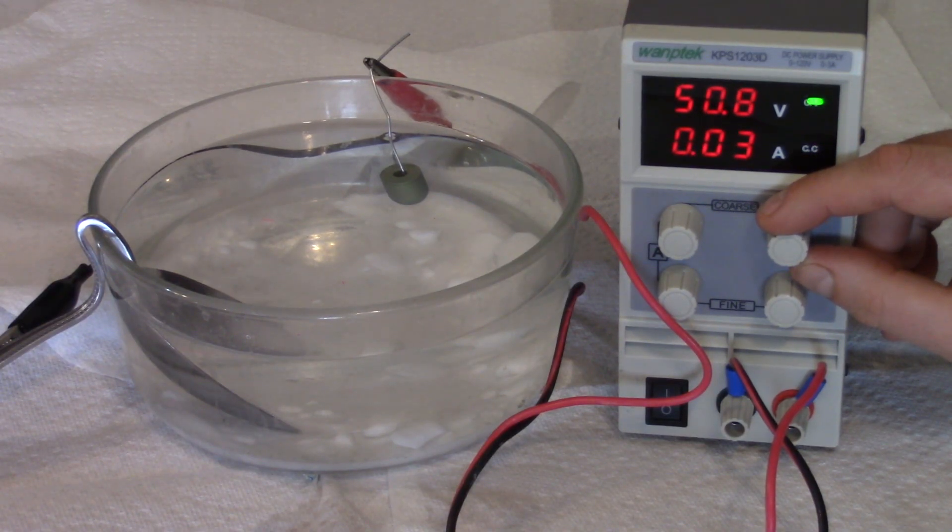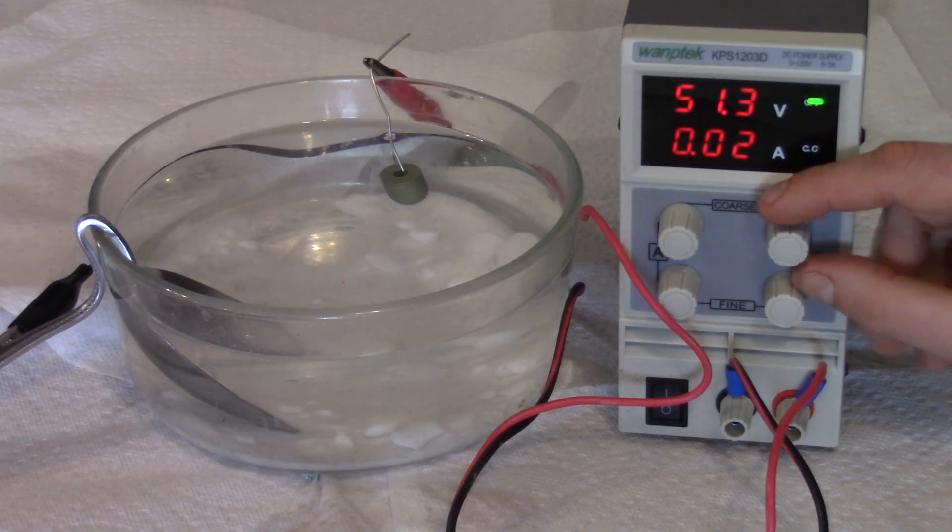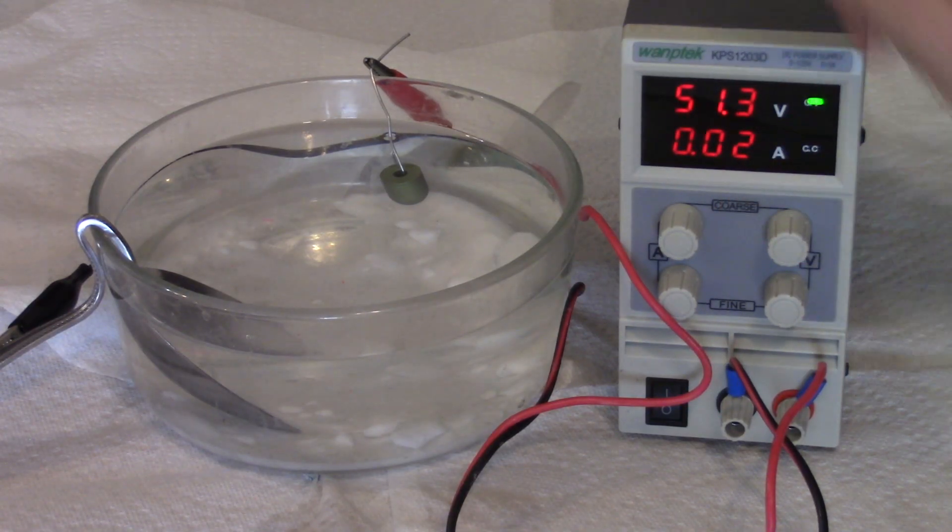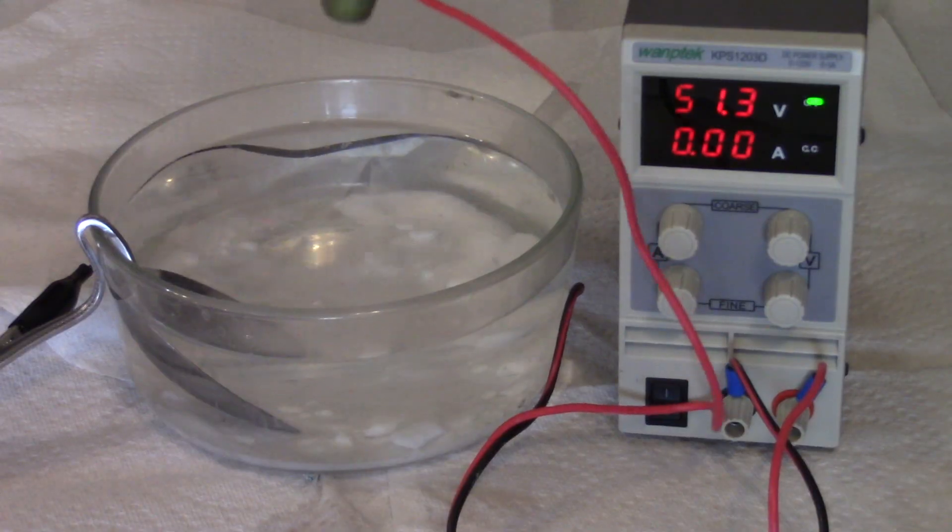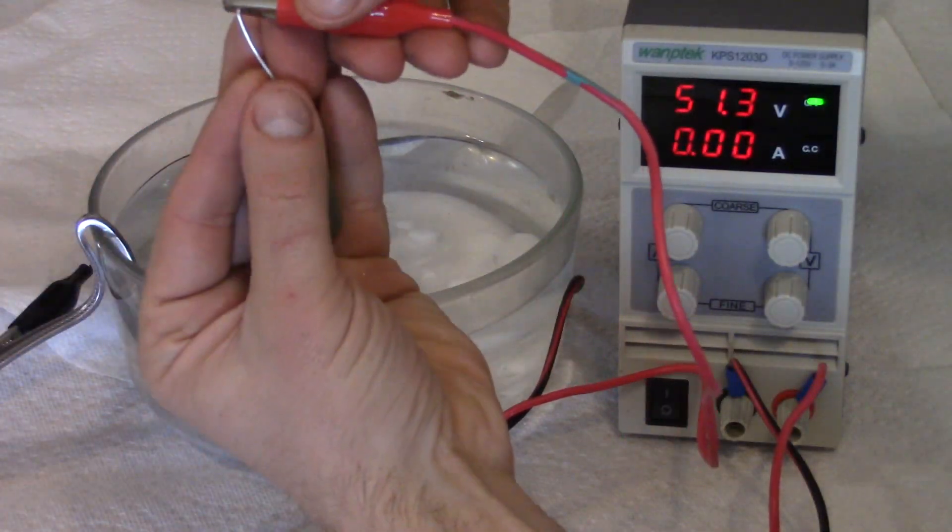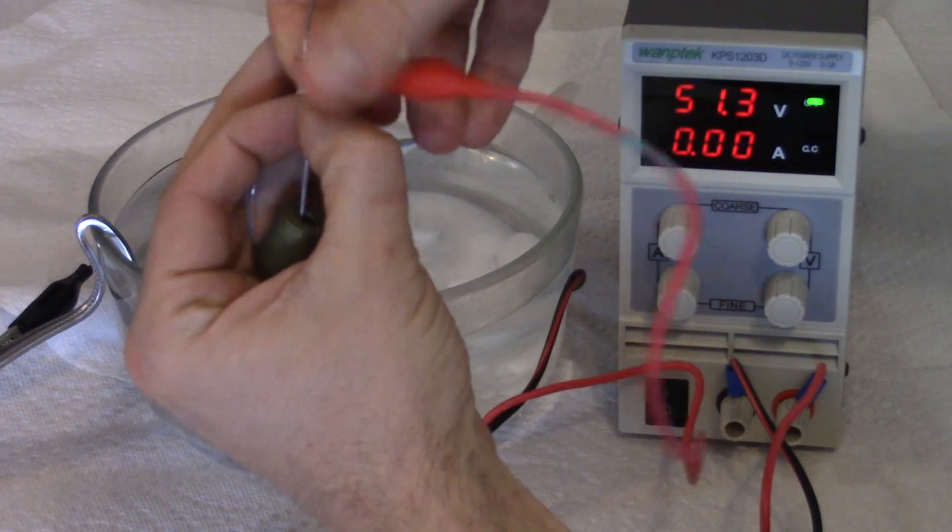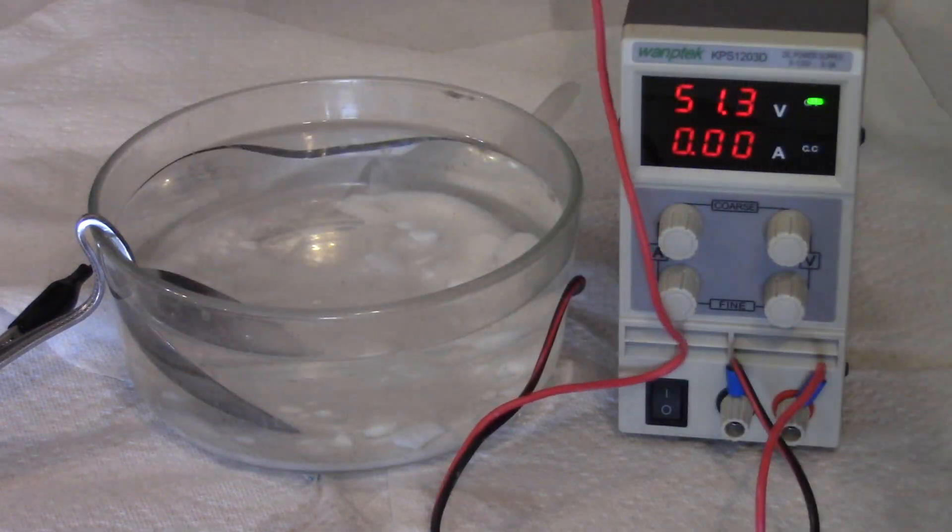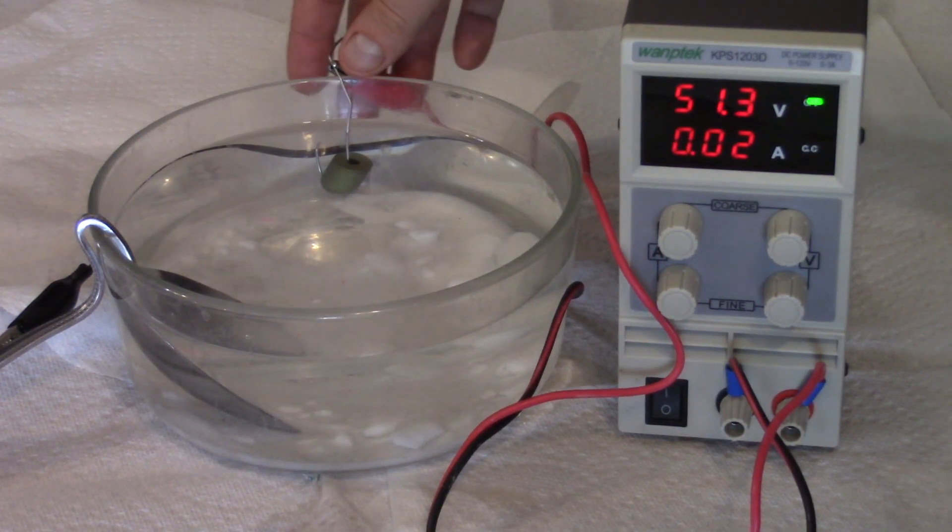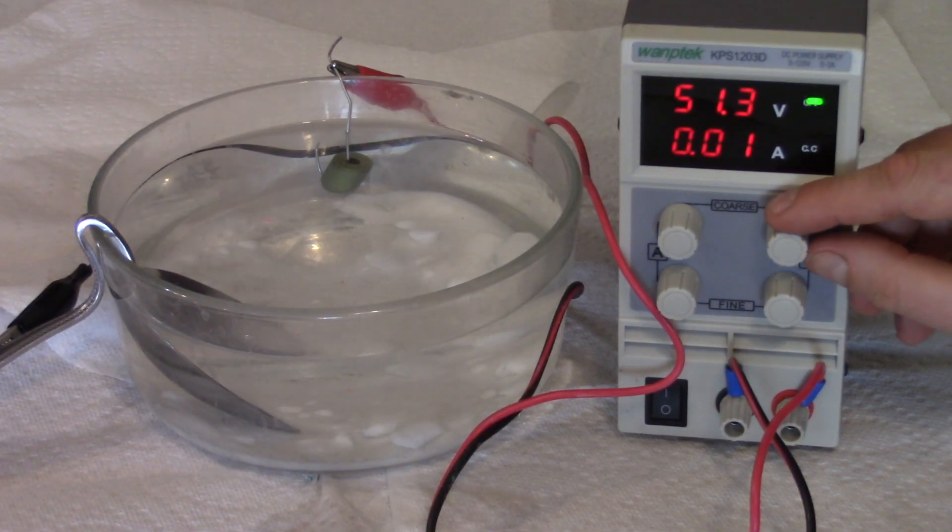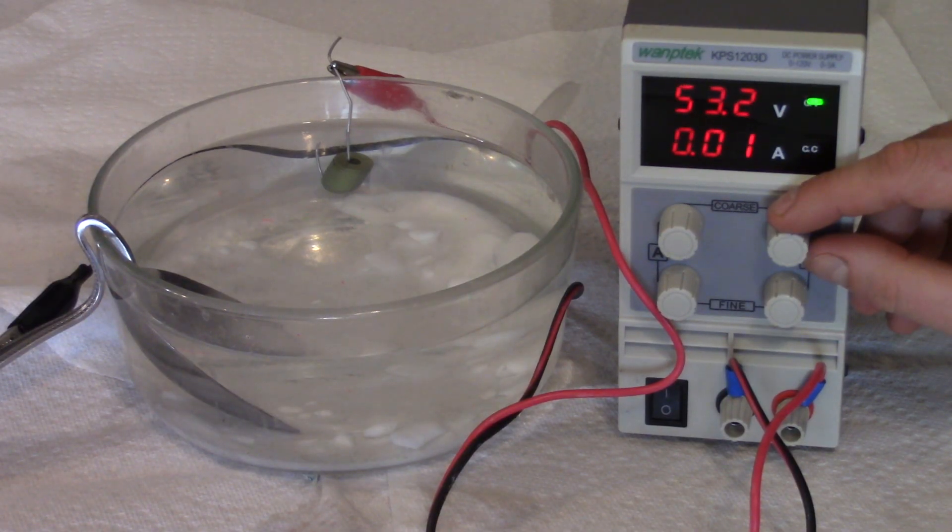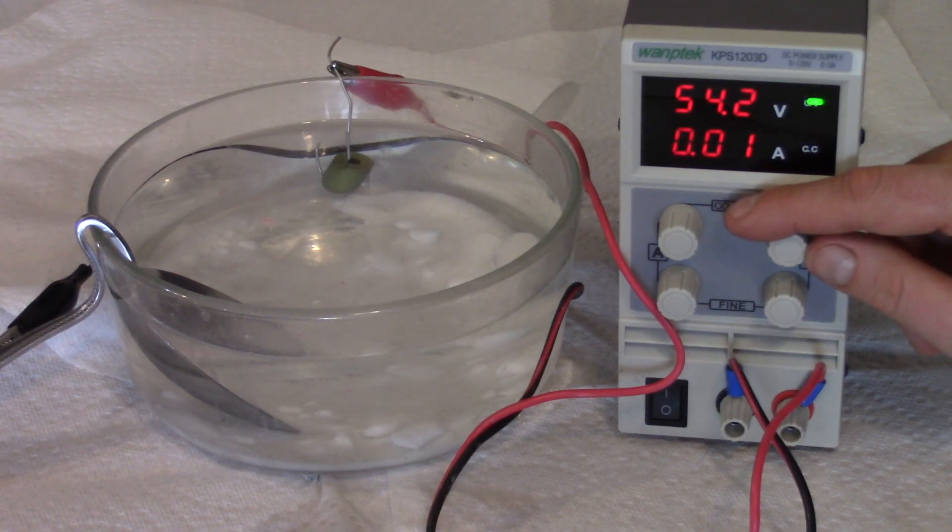I know as we get into the 60s it'll start to get pinks and purples. Here at 50 is like starting to go towards gold, kind of like an army green color. I might clip this, my wire was starting to break. It should fade more into a darker gold closer. We get to like 58-ish, 60 starts to go pink to purple.